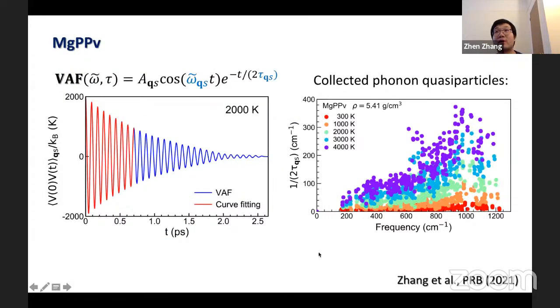To obtain phonon quasiparticle properties, the velocity autocorrelation functions were fitted to an exponentially decaying cosine function. The fitting was conducted until the oscillation amplitude decays to its half maximum. Conducting the fitting for several more oscillation periods leads to negligible changes in omega tilde and tau, meaning the convergence of the phonon quasiparticle properties. On the right, I show the collected phonon quasiparticles' line width versus renormalized frequencies at different temperatures.